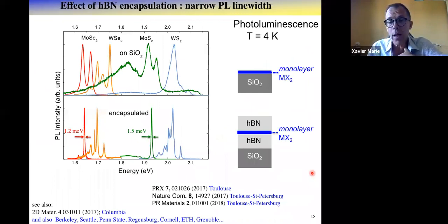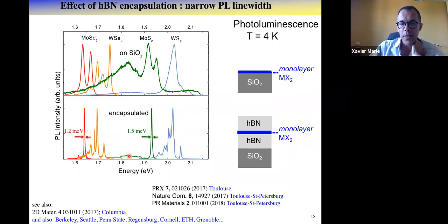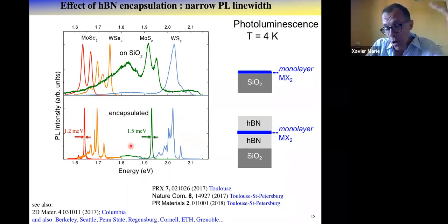In fact, this is not true only for WSe2. Basically, you can compare the first generation of sample and the encapsulated ones in hBN for almost all the family: WS2, MoS2, WSe2, MoSe2. This is the photoluminescence intensity as a function of energy, just normalized. And you see the very broad lines at low temperature you get when you are just transferred on silicon oxide, and the narrow lines you get when you encapsulate. Look, for instance, at MoS2 in green: you have these very broad lines, localized states, very broad. When you go into encapsulation, you have a very clean and narrow exciton line and much lower intensity of the recombination associated to localized or defect states.